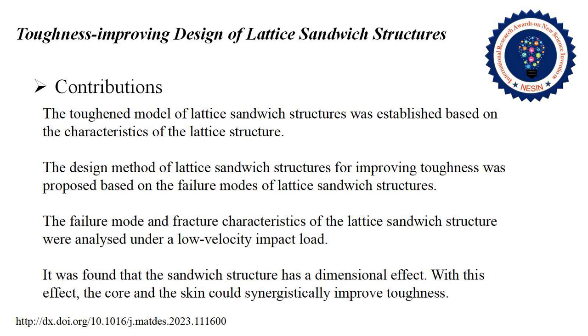In summary, in this study, we investigated the design strategy of lattice sandwich structures for systematically improving toughness. A toughened model of the lattice sandwich structure was established. A toughening design method was proposed based on the failure modes of the structure, and the synergies of the core and skin caused by the dimensional effect of the lattice were discussed. As a result, the variation trends of the impact energy calculated by simulation are consistent with the measured results. When the rod diameter decreases, the impact toughness of the structure decreases at first, then increases, and finally decreases.